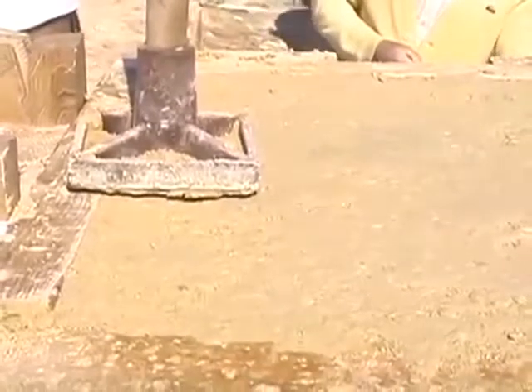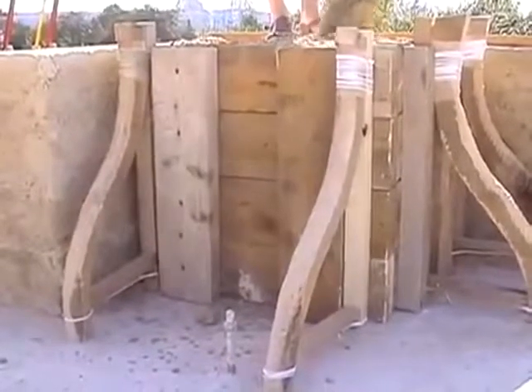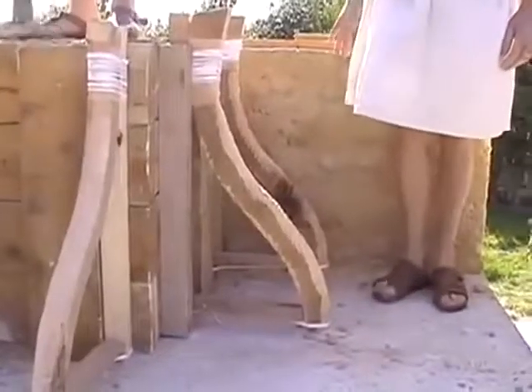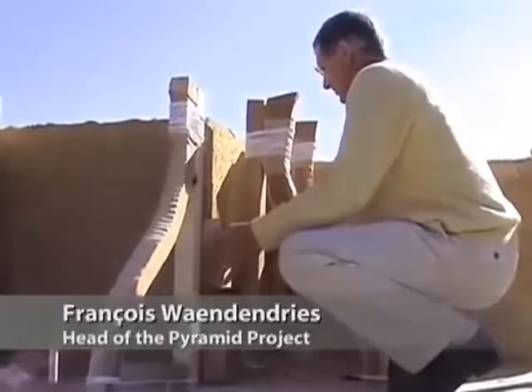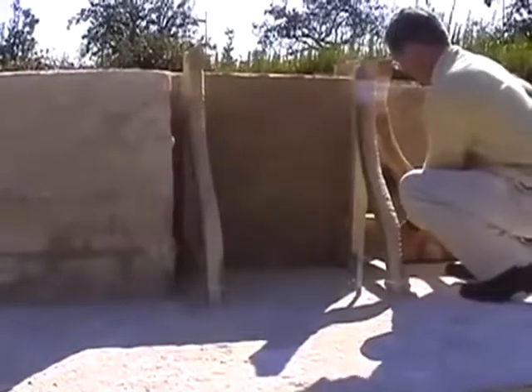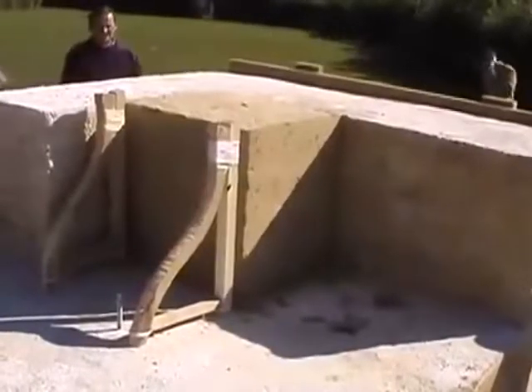When the climate is warm and beautiful, our crew rapidly produces a re-agglomerated limestone that proved strong, dense, and true to the mold's size and shape. The mold consists of small wooden boards which can be re-used many times for making other blocks. In this ideal weather, the whole process runs smoothly and is very simple. We remove the mold four hours later. The synthetic limestone looks like a natural stone — we observe no trace of wood grain.